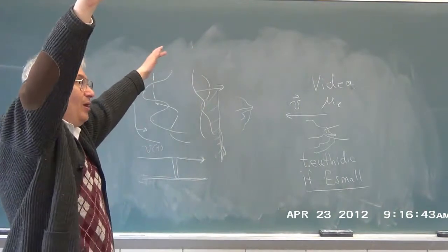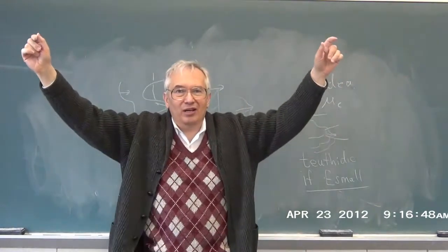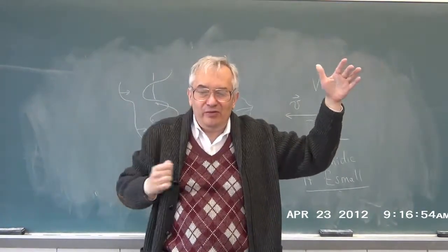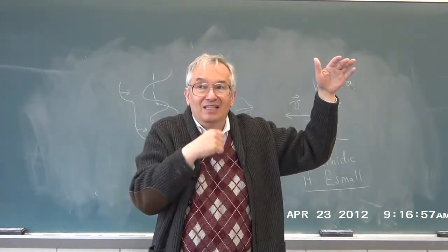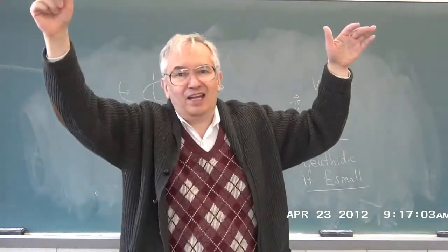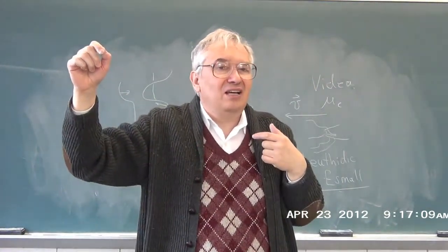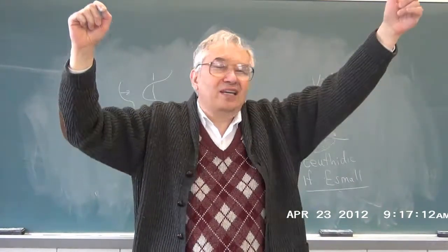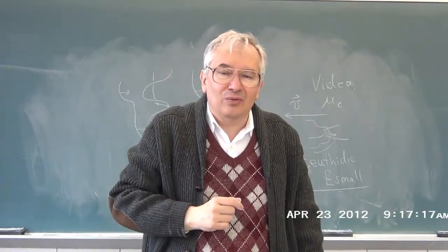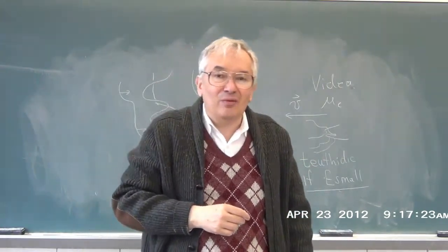Because if I am a star polymer, I am headed this way through a concentrated solution. If I encounter another polymer here, what I have to do is diffusively retract my arm in, stick it out on the far side, and now I've freed up this arm, and I can move ahead again until my arm encounters something, and then I have to retract my arm to disentangle it, and after I've retracted my arm, I can stick it out again on the far side of the obstacle. You notice if you try walking this way through any sort of set of obstacles, this is a very clumsy way to move, and I would be greatly slowed down.